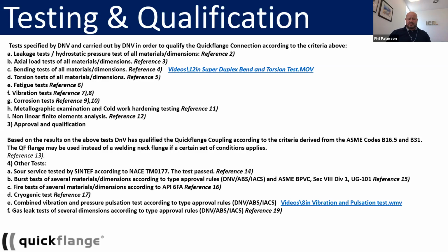We then did cryogenic testing for another client who was wanting to use it on a service where we just tested it at -100 degrees Celsius on stainless steel. One client wanted it tested at -110, and we did that test for them. So we have tested the product to -110 degrees Celsius. That said, we have limitations within our approval body, so it's -46 degrees Celsius to 205 degrees Celsius. But what we've done is we've tested the product way beyond its requirements.